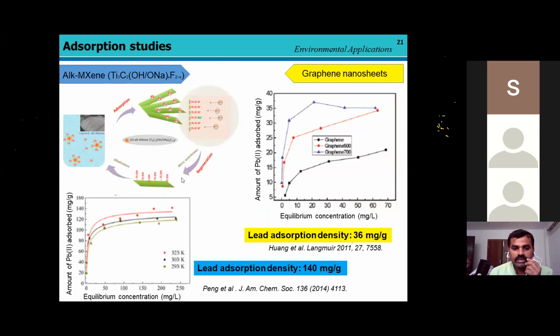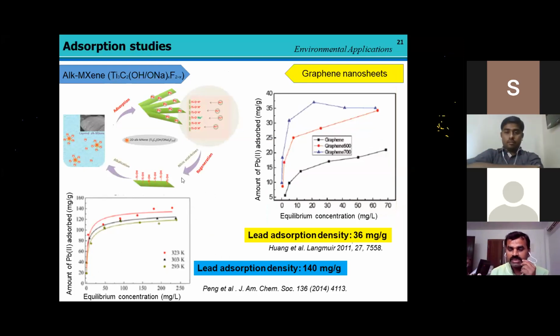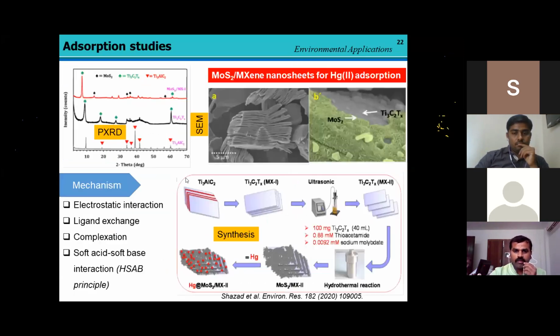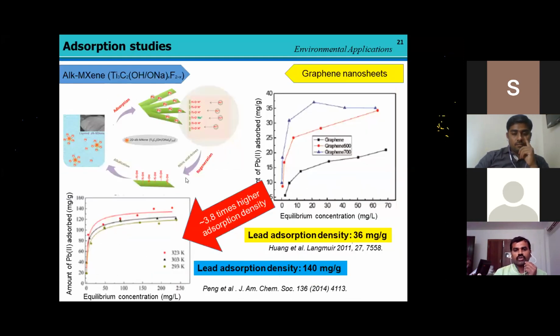We found that the adsorption capacity was much higher, 140 milligram per gram, using this sodium form of MXene, which was compared with some graphene-based materials. It shows a lesser amount, like 36 milligram per gram, with graphene-based materials, which is almost 4 times lower adsorption capacity of graphene oxide than the MXene-based materials. This is quite an advantage of MXene-based material.